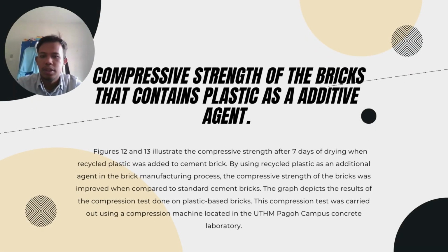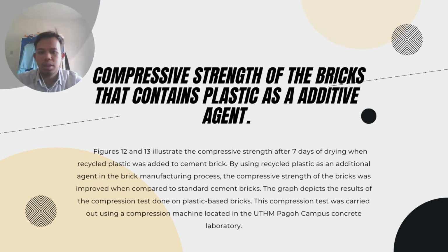Compressive strength of the brick that contains plastic as an additive agent. Figure 12 and 13 illustrate the compressive strength after 7 days of drying when recycled plastic was added to cement brick. By using recycled plastic as an additional agent in the brick manufacturing process, the compressive strength of the bricks was improved when compared to standard cement bricks. The graph depicts the result of the compression test done on plastic-based bricks. This compression test was carried out using a compression machine located in the UTHM Pagoh Campus concrete laboratory.